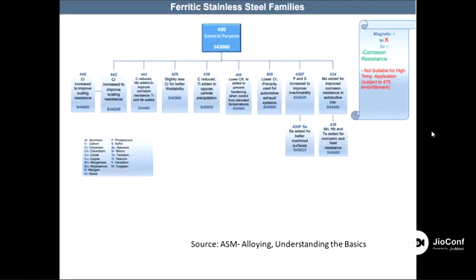When these ferritic steels are exposed to 475 degrees Celsius during service for a longer period of time, the ferrite decomposes into brittle phases like sigma and chi phases. So the structure becomes brittle, is no longer able to take the stresses, and failure of the structure takes place. So they are not suitable above 475 degrees Celsius.